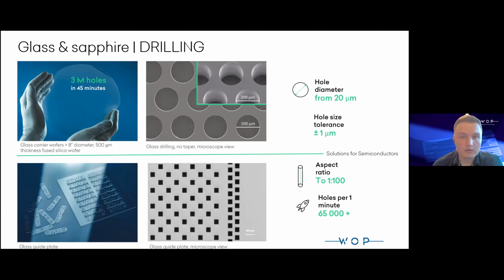And other limitations that we have, well, they're not really crucial, so to say, since the aspect ratio limitation in glass is 1 to 100, which is normally not nearly what's necessary. So we're really looking forward to testing the limits and seeing how it works best. Typical hole diameters are down to 20 micrometers. Working on case-by-case examples, these are possible to be even lower.